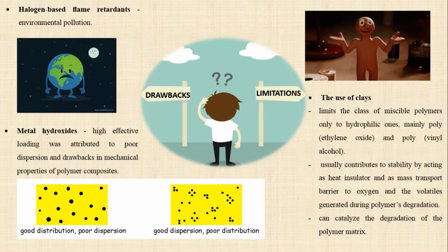On the other hand, the use of clays greatly limits the class of miscible polymers only to hydrophilic ones, mainly polyethylene oxide and polyvinyl alcohol. Clay usually contributes to stability by acting as heat insulator and as mass transport barrier to oxygen and the volatiles generated during polymer degradation. The improvement in thermal stability may be limited, since the clay itself or the decomposition products of the organic modifier can catalyze the degradation of the polymer matrix.